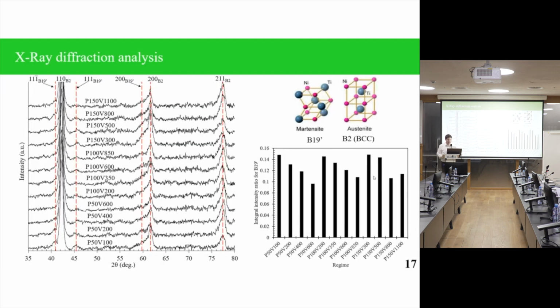And finally, to prove that we do not have any secondary phases after the manufacturing of samples, X-ray diffraction analysis was performed. Here we can see that all peaks of the XRD spectra are actually from the B2 and B19 phases. Based on the integral intensity ratio between all peaks, we can even evaluate the ratio of volume fraction between these phases. And also we have the dependence on the regimes.